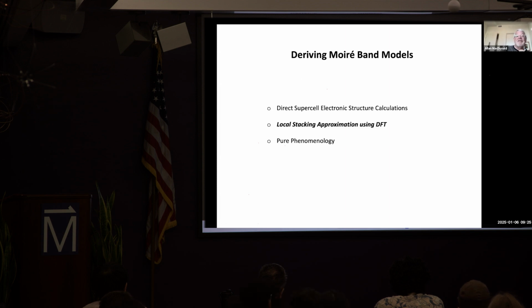Whenever I have these moiré patterns, and I have these two layers, primed and unprimed, if you like, they have different reciprocal lattice vectors, but similar. If there's a commensurate relationship between those reciprocal lattice vectors, that means that eventually the set of points that you generate in momentum space, the set of possible momentum transfers, doesn't fully occupy all possible momentum transfers. Instead, you get a crystalline array with a large period.